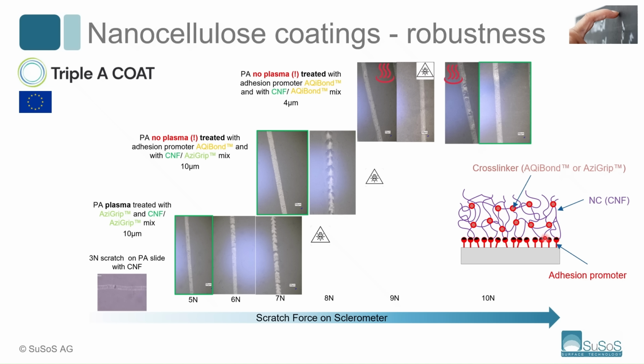If we now use an adhesion promoter, in this case we use the plasma protocol with the azide polymer with the azide group as an adhesion promoter and also as the cross-linker, so mixed with the nanocellulose, we achieve far better scratch resistance. However, if we try our non-plasma protocol, which would be far more suitable to be used in the bus, and we try using the AQIBond with the low temperature activation azide group with the CNF mixed with the cross-linker polymer that has the azide group inside, we can already go to approximately 7 Newton upon UV curing, which is increasingly better than the previous case.